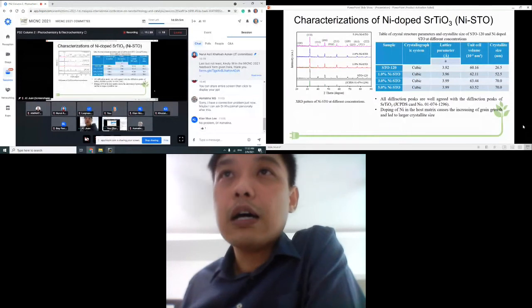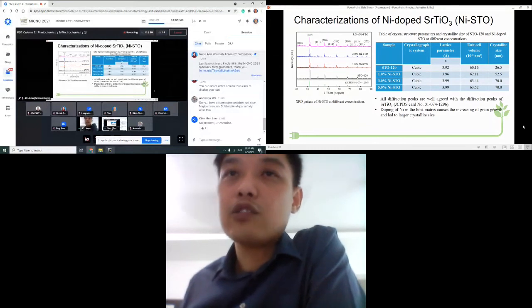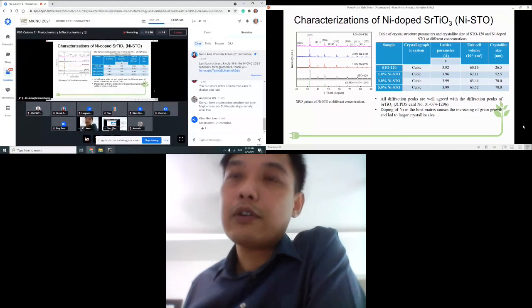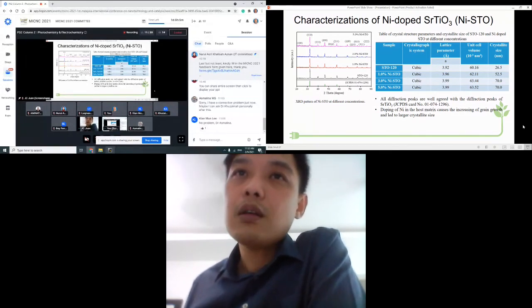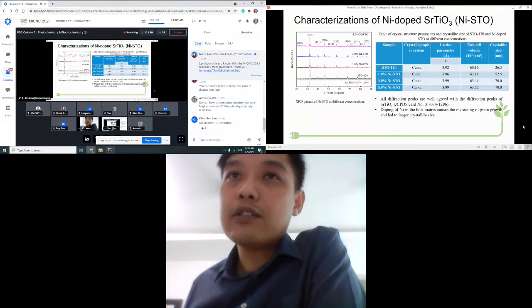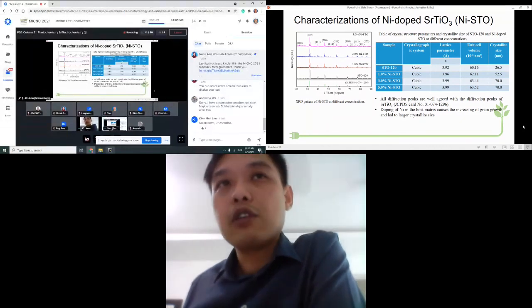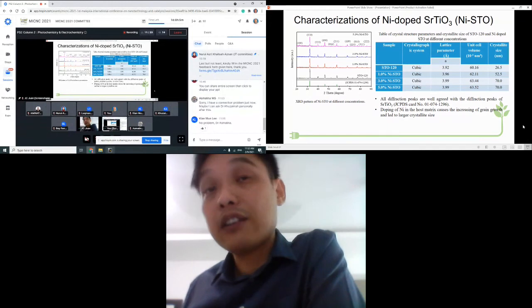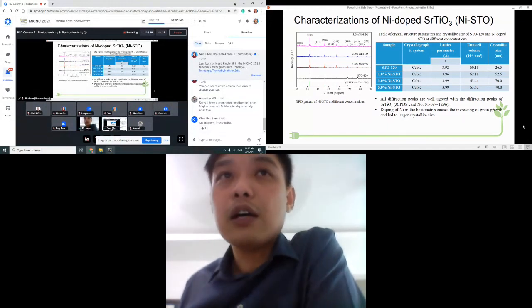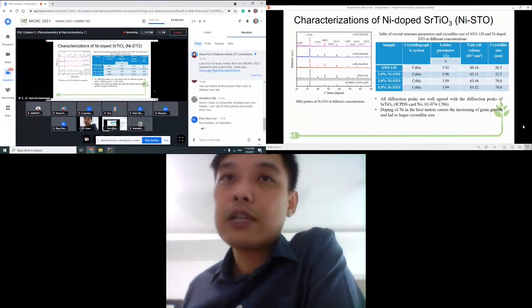So what we found here, first we have to synthesize this SrTiO3 at 120 degrees C. You may ask why we choose 120 degrees C, because this is the best temperature to produce the strontium titanate with good conductivity and good capacity. We found that at 120 degrees C, we're able to introduce oxygen vacancy that enhances the current density. And then we do some doping here. We vary the concentration of the dopants from 1% to 5%.